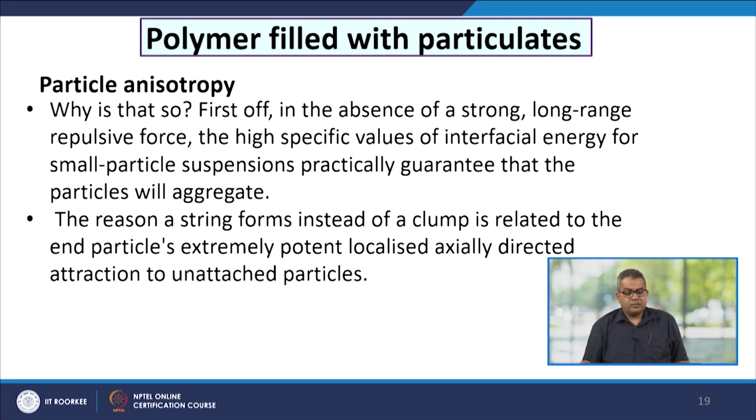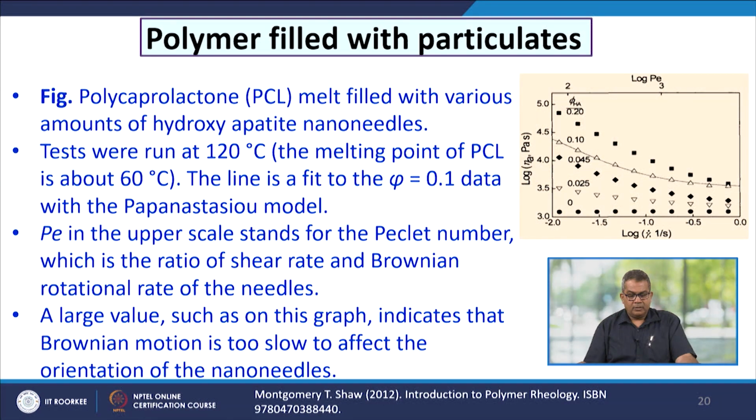Why is it so? First of all, in the absence of a strong long range repulsive force, the high specific values of interfacial energy of a small particle suspension practically guarantee that the particles will aggregate. The reason a string forms instead of a clump is related to the end particle's extremely potent, localized, axially directed attraction to unattached particles.